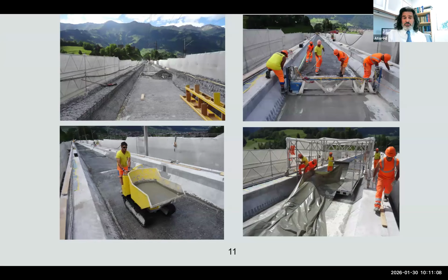In Europe, they have used it for retrofit, cast-in-place version, not the spray. Cast-in-place, and the thing is that when you wrap an existing bridge or column or something with the UHPC, the end product actually sometimes becomes even much better than the original structure, because the material is very durable, and we will discuss that, and it is very strong. I mean, we are talking about 25, 28, 32,000 psi concrete in 28 days.